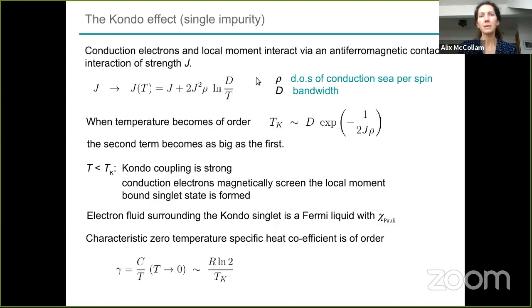And the interaction of these local moments with the conduction electrons is what is giving us most of the physics, or most of the characteristic physics in these materials. So the conduction electrons and the moments interact. There's an exchange interaction or an antiferromagnetic interaction which has some strength. So this J is now the coupling between the local moment and the conduction electrons. So the F moment and the conduction electrons. And this develops a temperature dependence, or a form that looks like this.